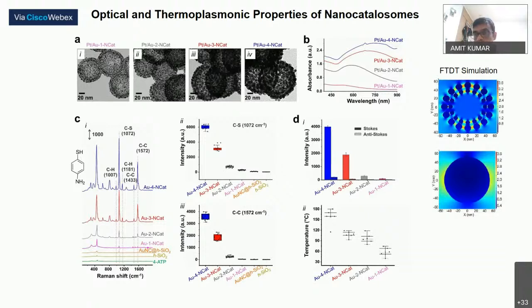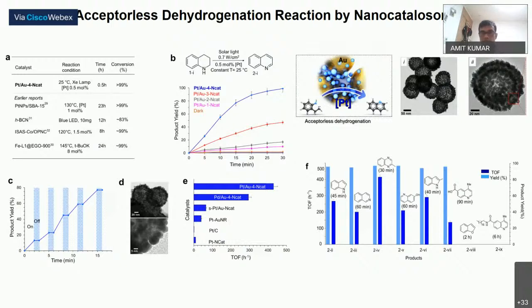And this FDTD simulation is a calculation. So it also located the position of hot spots in the bilayer region of the nanoparticle. And as compared to the simple sphere of the same size, the electromagnetic field concentration is very, very high in such structures. So then we applied these bilayer structures for dehydrogenation reactions.